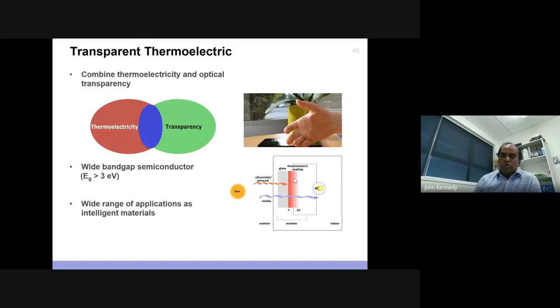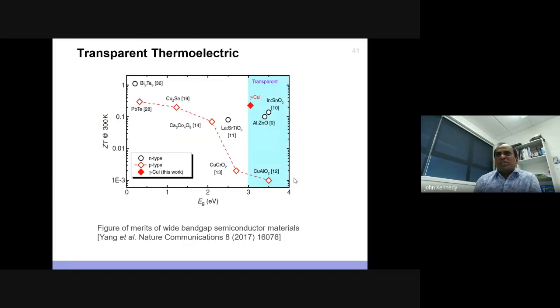In a new concept, we looked at what transparent thermoelectric materials are available. If you look at this diagram, you need a band gap somewhere between 3 and 4, because in order to get the figure of merit high, you need a high Seebeck coefficient and electrical conductivity, and you also have to reduce the thermal conductivity. Then you have to maintain the optical transparency. The materials proposed are copper iodide, copper aluminum oxide, and even aluminum zinc oxide, which come under that kind of band gap region.